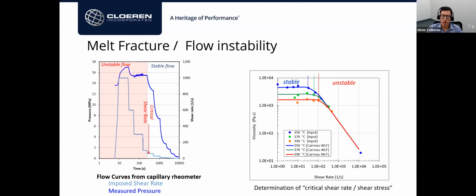That's one thing. If now we have a problem with the volatiles, we have to identify: is the melt temperature too high? Do we have too much shear heating? Because those BOPP processes are huge outputs, and I've seen very, very high rates. We're talking about 5 tons, or even, let me think about it, yeah, it's like a 1.2 meter die and it's over 6 tons an hour. Huge output. So a lot of shear through the system could be the issue. So maybe some ways to lower the viscosity of the melt, looking at a slightly higher MFR.